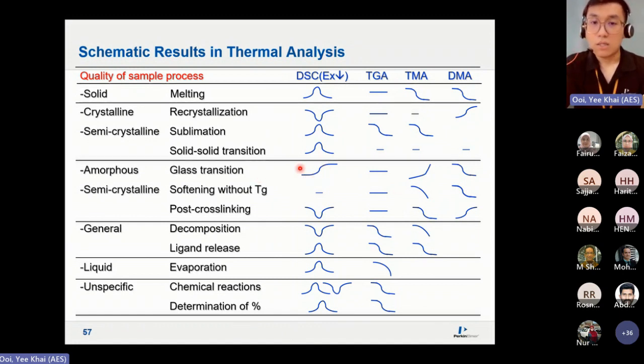Now, glass transition being a weak transition, notice in TGA there is no change of the weight. Even melting is also the same. In TGA, there is no change. But the melting peak is always a sharp transition in DSC. So exothermic going down means melting is endothermic going up. So always read your y-axis first. If it says endo down, that means it's going to be going down. That will be melting. But normally I will represent it in endo up.